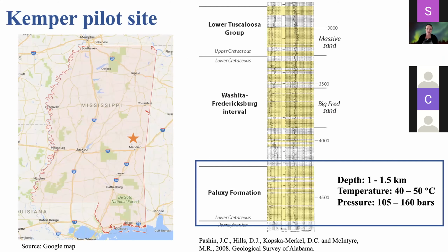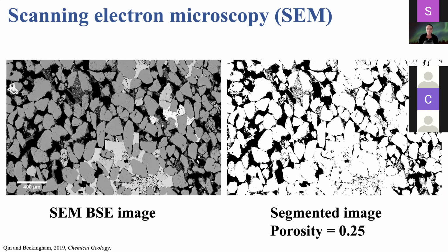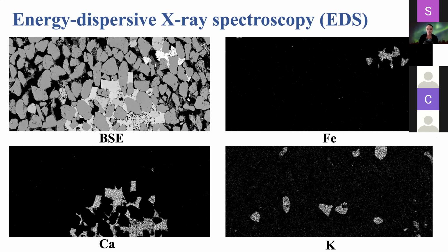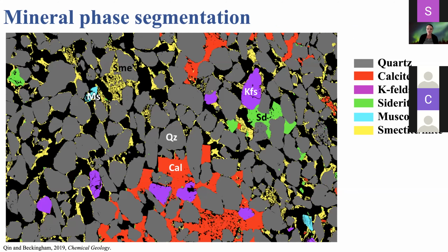We are going to look at a sample from the Paluxy Formation. This is from a potential CO2 storage plant in Kemper County, Mississippi. Here we used SEM imaging to enhance our understanding of the pore structure at high resolution. We can get porosity information for this sample as shown in the segmented image on the right. We can then combine this with EDS imaging, which provides elemental maps to understand the distribution of minerals within the sample. So in this image, each color corresponds to a different mineral phase.